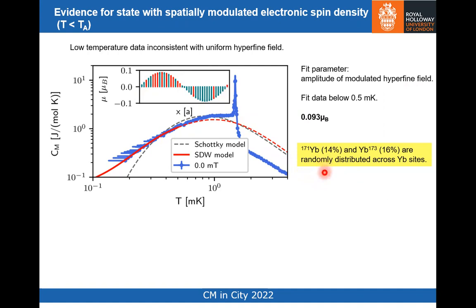Remember, and this is key, that we have 14% 171 ytterbium and 16% 173 ytterbium, and obviously they're randomly distributed across the ytterbium sites. So any modulation in the electronic moment, such as this, is going to give you a random modulation of the hyperfine field seen at those ytterbium sites. So the nuclear spins then are a diagnostic for spatially modulated electron spin density, which is appearing at temperatures less than TA. And just by fitting the low temperature data, where it would be natural to assume that the amplitude of that modulation is no longer temperature dependent, we find that the amplitude is 0.093 μB, which is very similar to the 0.1 μB that you get at the quantum critical point induced by an external magnetic field.